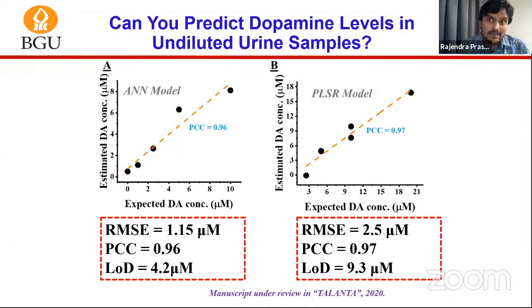We use these two algorithms to check the performance of our sensor array that we developed for the detection of dopamine in undiluted urine samples. Using the ANN model for the test set, we have the RMSE, the root mean square error, that is very low, 1.15, and the limit of detection is 4.2 micromolar. For this analysis, we have hundreds of samples, spiked with 0 to 10 micromole per liter into healthy volunteers' urine samples. Around 100 samples were used in this study, with different labels and different combinations.